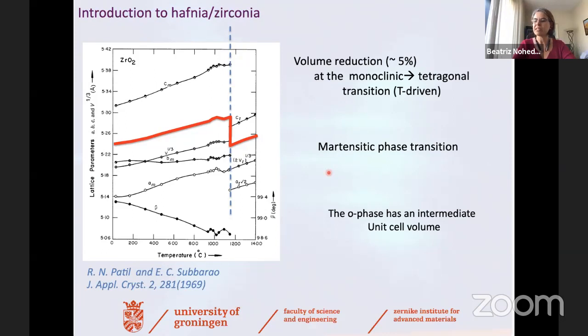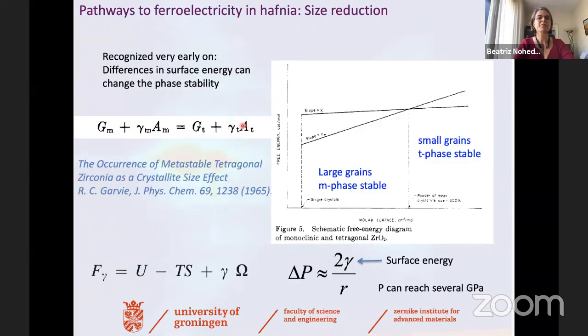So the route towards stabilizing the orthorhombic phase seemed to be trying to get the tetragonal material and then changing either doping or different aspects that we'll see later in order to go into the orthorhombic phase. If one would stabilize the monoclinic phase originally, this energy minimum is too deep to be able to later go into the orthorhombic ferroelectric phase. So all this, of course, took many years to figure out all these details. But it was clear that in order to stabilize this ferroelectric phase, one needed small sizes.